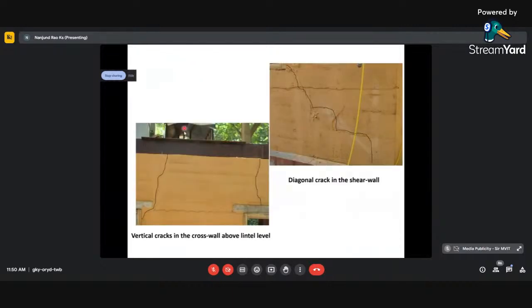What happened? You see from the lintel level two vertical cracks here, horizontal crack here, and also the in-plane shear wall had a diagonal crack from sill to the plinth level, like this, step kind. So this is the joint actually, this is the rammed earth joint, and the mold also we had to move from one to other, and that is how it moves like this, like a step.